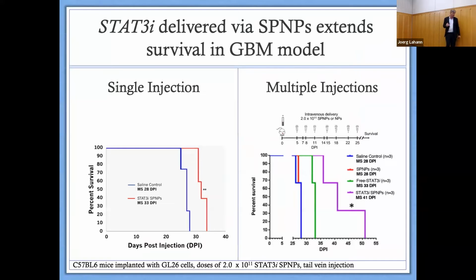And then Maria's group basically took those particles and injected them into mice that had the intracranial brain tumor. These are GL26 cells. The dose is about 10 to the 11 particles, single injection, and we saw statistically increased survival. Typically, this is an aggressive tumor, so the mice die about 28 days into the tumor. And we saw a sizable, but maybe not super exciting, extension in survival, but it's statistically significant.